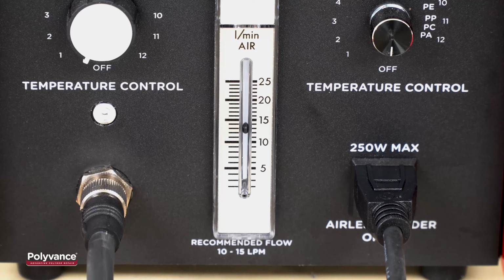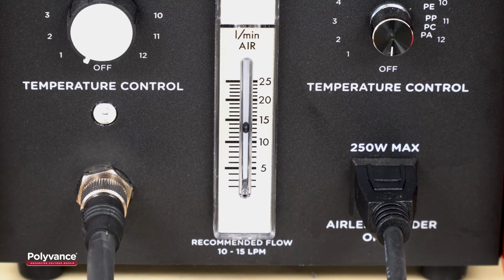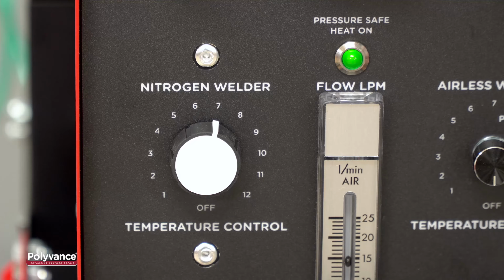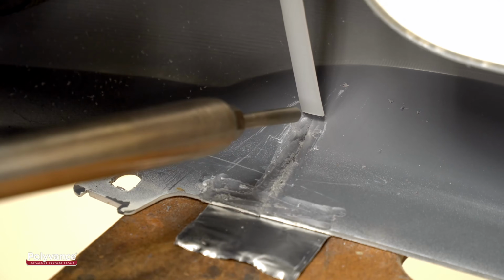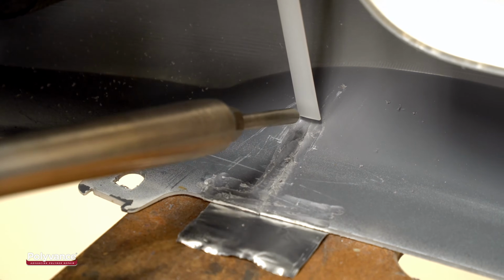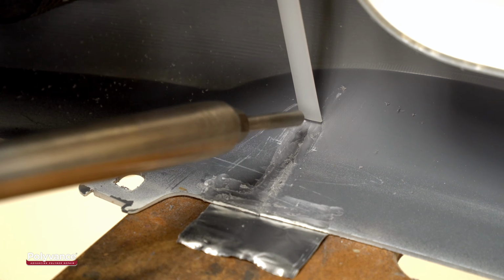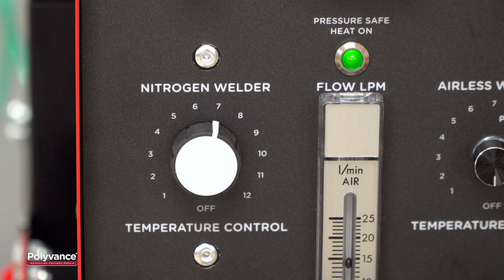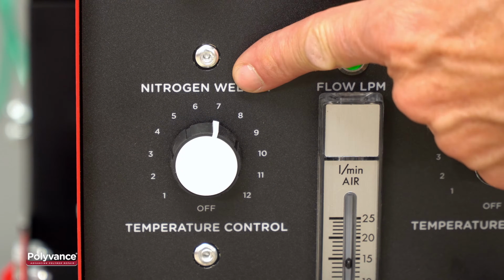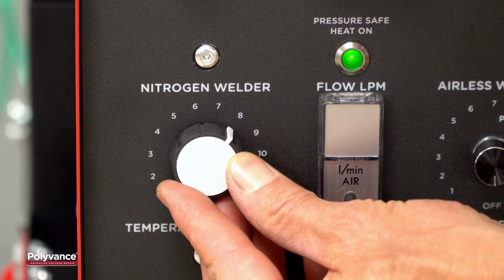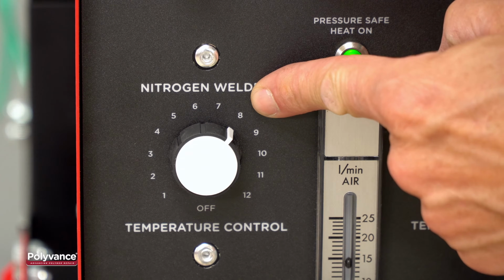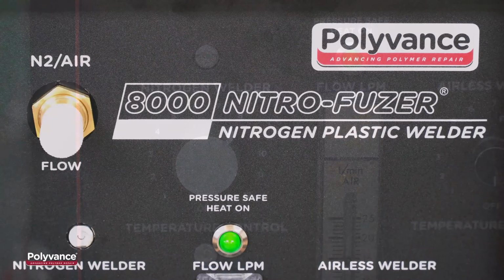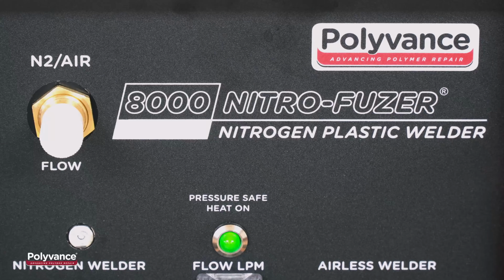If your nitrogen welder is not getting hot enough, check that your nitrogen flow is about 12 liters per minute and that the temperature is set at about 7 or 8. At this setting, it should get hot enough to gloss over polypropylene in about 3 to 5 seconds. Normally, if the welder is not getting hot enough, it's because the flow is set too high and the temperature hasn't been increased accordingly.